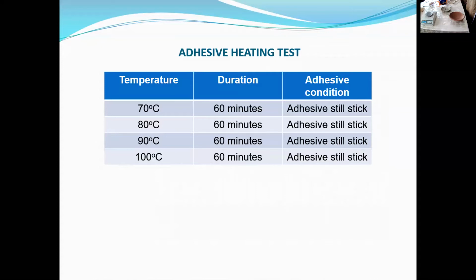We also run some heating tests on the adhesive. We put the joint fragments, the repaired ceramic, into an oven with the temperature between 70 degrees Celsius to 100 degrees Celsius, for 60 minutes for each temperature range. When the repaired ceramic is heated up in the oven, the adhesive remains stick, so the joint part is not getting loose.